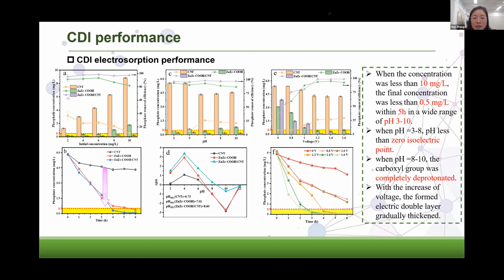This is because zinc and zirconium can be combined with phosphate through ligand exchange. And the existence of the carboxyl group increases the adsorption sites of phosphate. Besides, when the pH was in the range of 3 to 8, the pH was less than the isoelectric point, so the electrode surface still had more positive charges. So the phosphate removal efficiency was high.